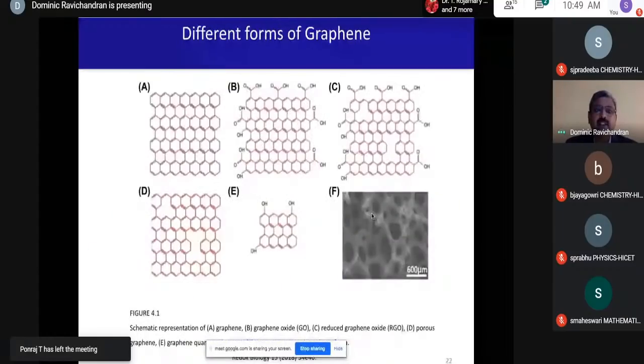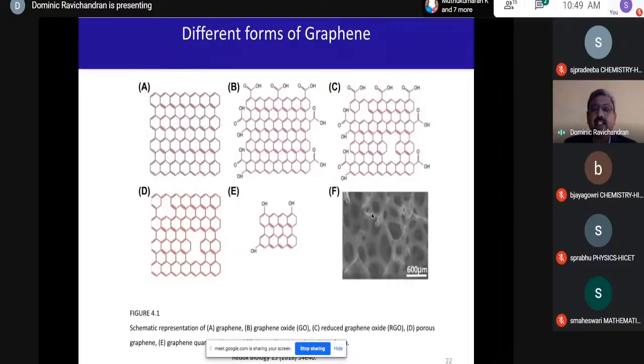The different forms of graphene that we have are graphene, indicated by A, and graphene oxide. When you oxidize graphene, what you get is graphene oxide, indicated by B, where you see oxygens around. And C is a reduced form of graphene oxide, where we can reduce this graphene oxide using a reducing agent like sodium borohydride. This removes most of the oxygen to give the required functionalities.